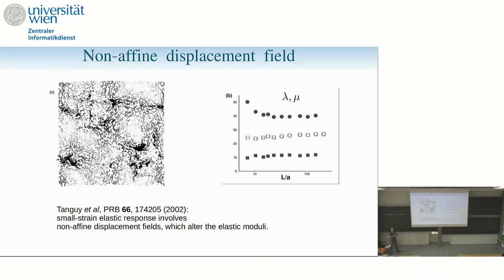And if you're a theoretician, one thing you can do in order to measure a modulus is assume that if you strain your system, well, you talked about non-affinity. I'll give a bit more detail on that. So Luca talked about that. But you could assume that the response of the system is affine. Affine means that you're shearing your system, and all the particles follow just the prescribed average affine deformation. You apply a strain, and you suppose that you have a displacement field which is exactly that prescribed by the average strain. So that's the affine motion.